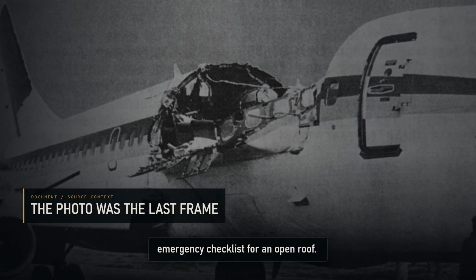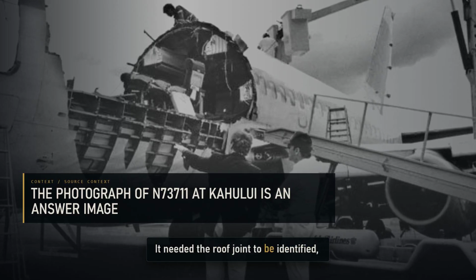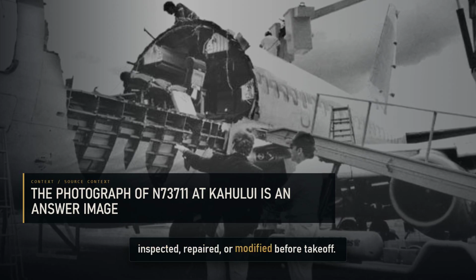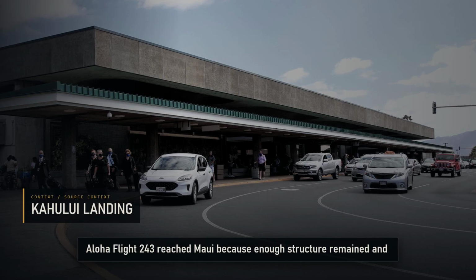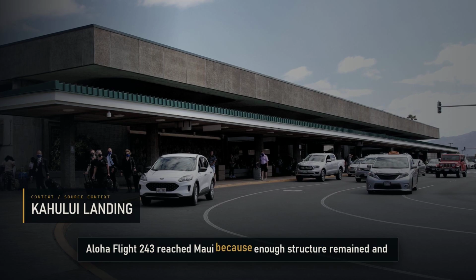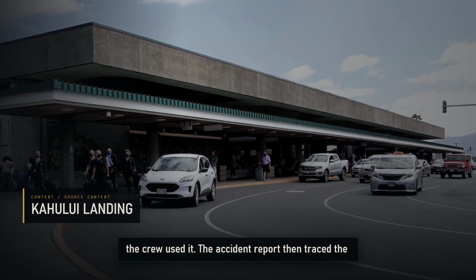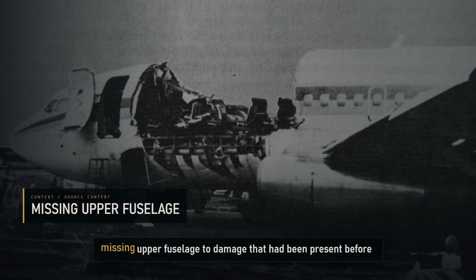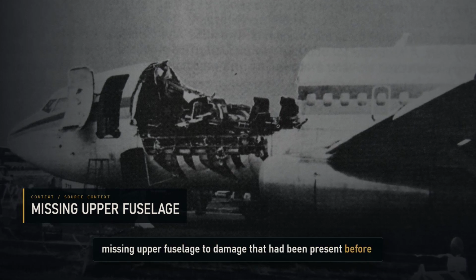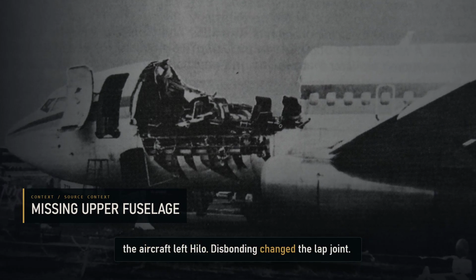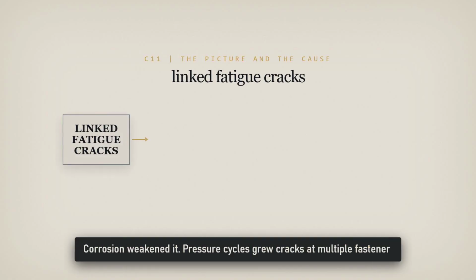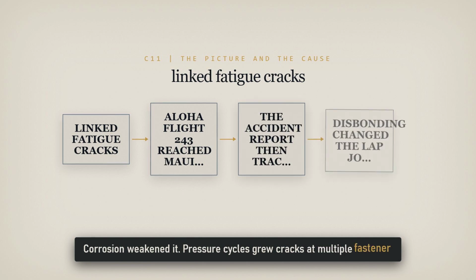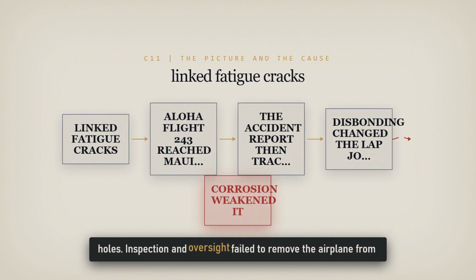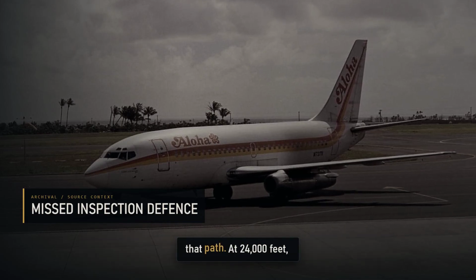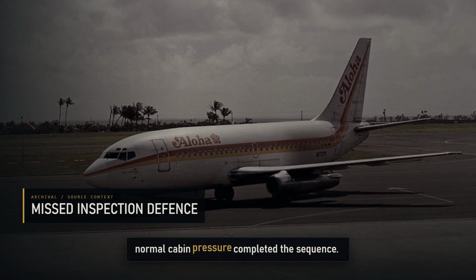Flight 243 did not need a stronger emergency checklist for an open roof. It needed the roof joint to be identified, inspected, repaired, or modified before takeoff. Aloha Flight 243 reached Maui because enough structure remained and the crew used it. The accident report then traced the missing upper fuselage to damage that had been present before the aircraft left Hilo. Disbonding changed the lap joint. Corrosion weakened it. Pressure cycles grew cracks at multiple fastener holes. Inspection and oversight failed to remove the airplane from that path. At 24,000 feet, normal cabin pressure completed the sequence.